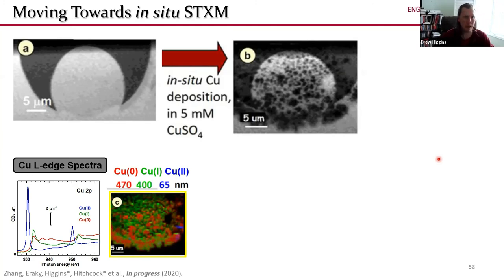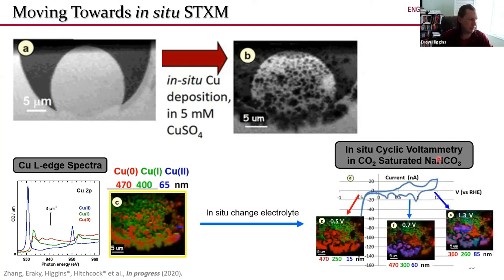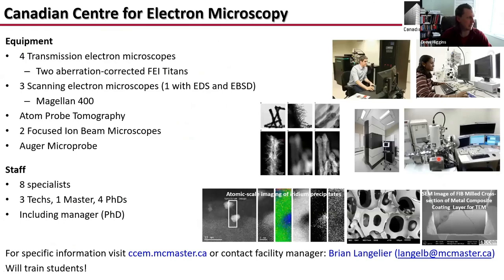And then we want to apply electrochemical bias or electrochemical potentials, such as those that would be seen under electrochemical conditions. And what we found is that we could track the morphology as well as the oxidation state of copper under these electrochemical conditions. And so really the next stage of this research is to implement these techniques to understand these nickel nitrogen carbon catalysts, what their structure is, what their properties and what their morphologies are like under electrochemical CO2 conditions. I see I'm getting late on time.